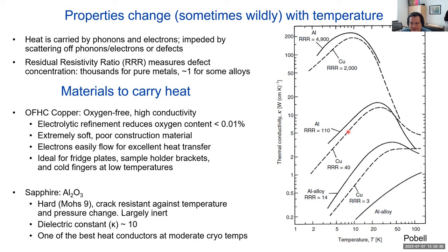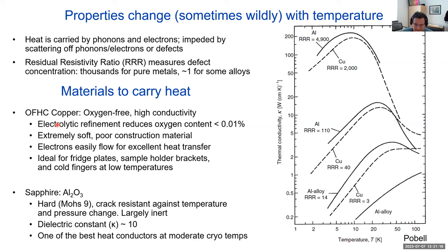Aluminum alloy with a very low RRR becomes less and less thermally conductive as you cool it down, whereas as the RRR rises, you see aluminum and copper crossing each other back and forth. Copper is notionally a somewhat better conductor than aluminum at room temperature, but at 10 Kelvin, it matters far more how clean the copper is than whether it's copper or aluminum. For that reason, the number one way to carry heat in any cryo system is what's called OFHC copper — oxygen-free high-conductivity copper. You can buy it off McMaster. It's basically been purified. It is a terrible construction material — it's extremely soft — but because it has really good thermal conductivity, basically everything is built out of it.